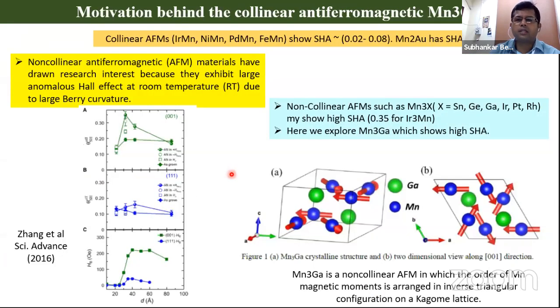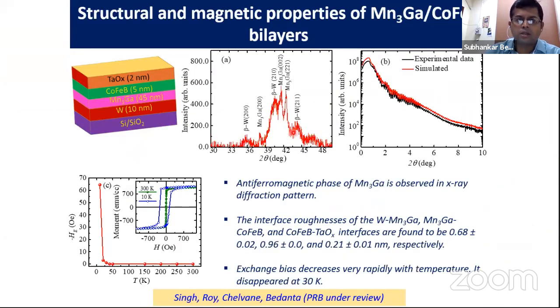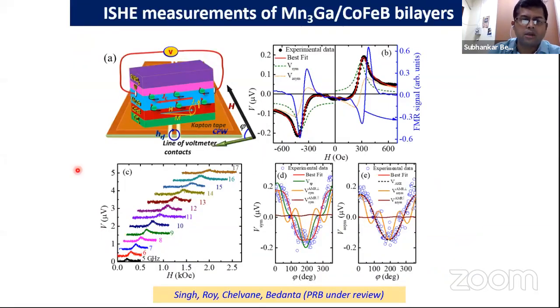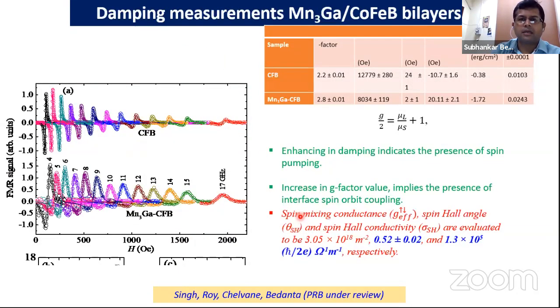Now, just the last 1 minute, I would like to spend on these very interesting non-collinear antiferromagnets. Some of you may know that this iridium manganese 3 is a recently discovered antiferromagnet, and a lot of research is happening on similar compounds, Mn3X basically, Sn, Ge, gallium, and so on. So we have focused on manganese gallium, and we have successfully prepared the manganese gallium films. Here the X-ray nicely shows that the manganese gallium phase is forming, and I don't have much time, and we have taken again cobalt iron boron as a spin source, and we try to do the spin pumping. Here is the frequency dependence of the voltage, and we do some analysis, and we found that the spin Hall angle for this system, that's I think the take home message, is about 0.52.